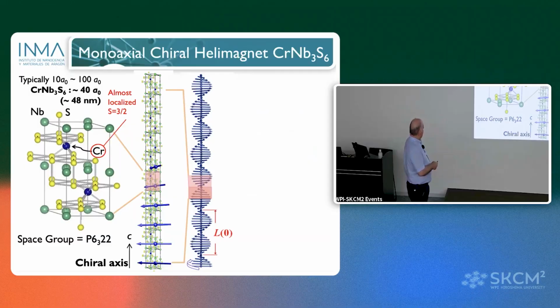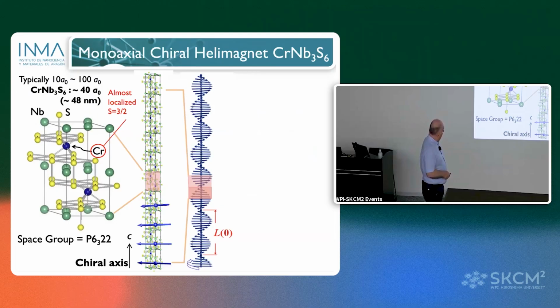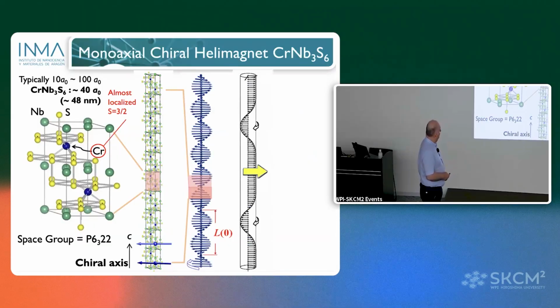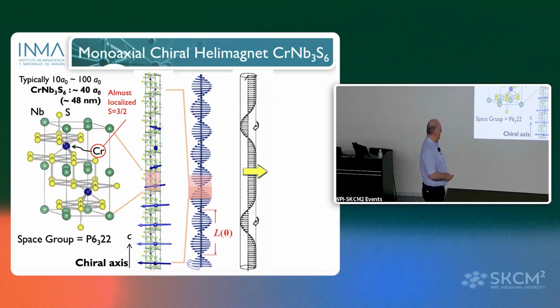Then, this is chromium niobium disulfide, a uniaxial helimagnet. And here we have the helix. It's a very long range helix. You can see here many unit lattices are needed to form the period. And then if you apply the magnetic field perpendicular to the chiral axis, this period is becoming larger and larger, like this. And at the end, you will have one ferromagnetic system because the period is going to infinite.